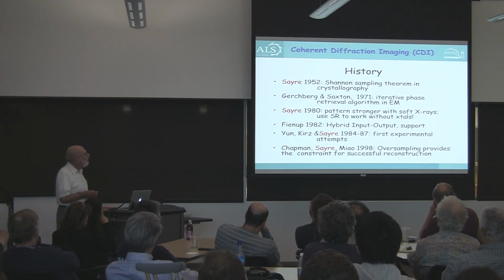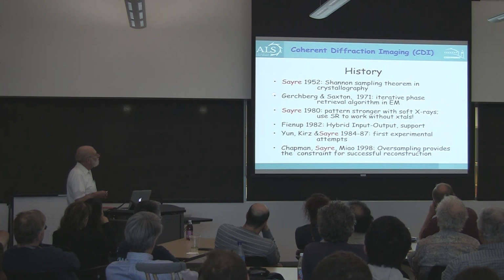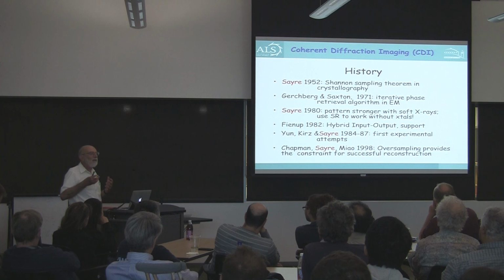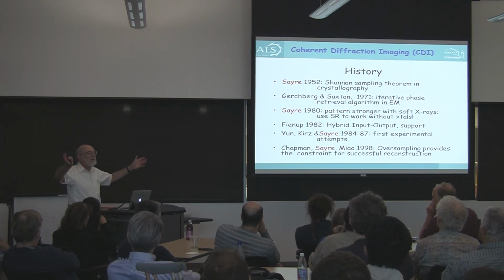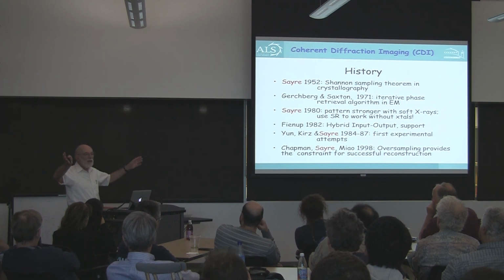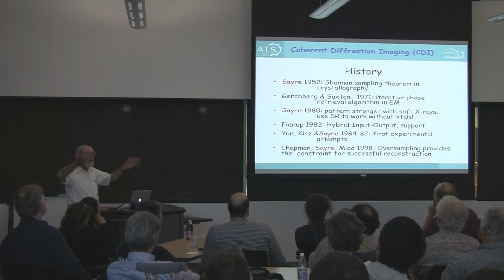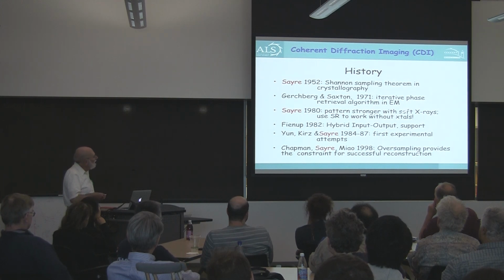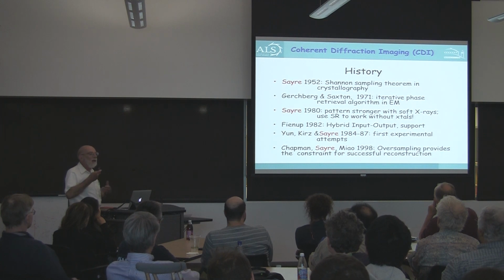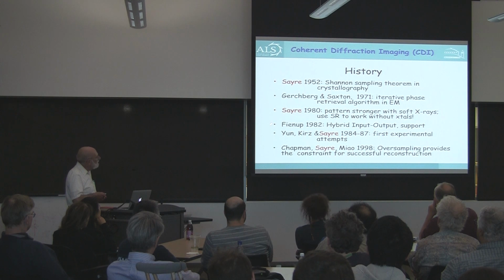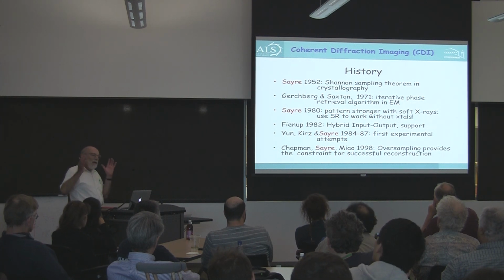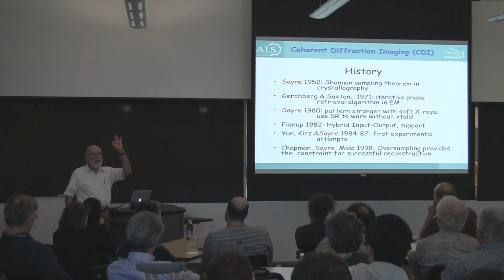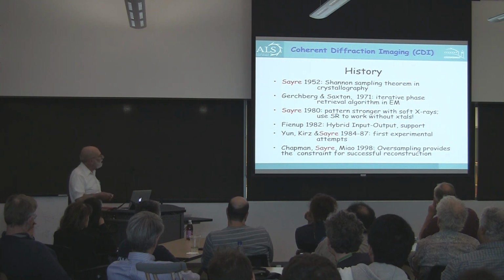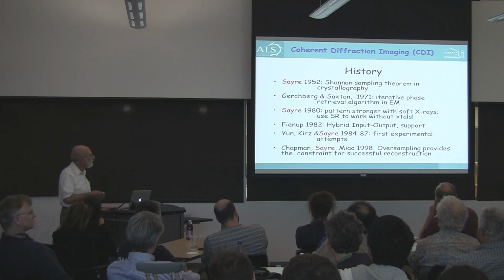Now, the history of this idea has a whole lot to do with David Sayre, who over more than half a century has been pursuing this idea, starting with a paper in 1952, where he showed that if all you can do is record Bragg peaks from a crystal, there is not enough information to make a reconstruction on the basis of that alone. And if you could just record information between the Bragg peaks, that would be very helpful. In the subsequent decades, there was a lot of work done in algorithm development, which culminated in the paper by James Fienup in 1982, where he showed that prior knowledge that your object of interest is limited in size and there is nothing around it, which he called finite support, would make it possible to use an algorithm which he called the hybrid input-output algorithm to make a reconstruction.